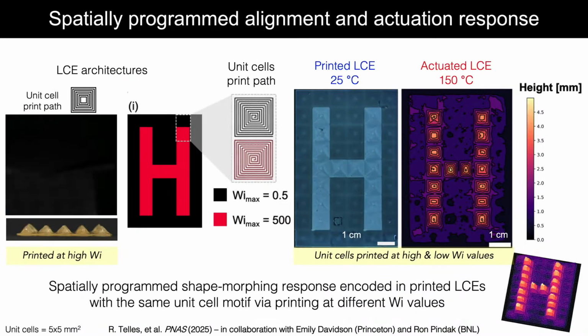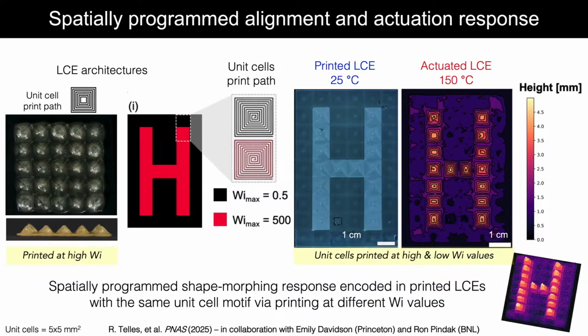And depending on the degree of alignment, we're not only changing the mechanical properties of these structures, the more aligned, the more stiff and the less flexible, but we can also locally encode the actuation strain. So at low degrees of alignment, there's very little change in the actuation. We heat it up, it doesn't really contract or expand laterally. Whereas if we encode this high degree of alignment, as I said, we get about a 40% contraction along that printing direction.